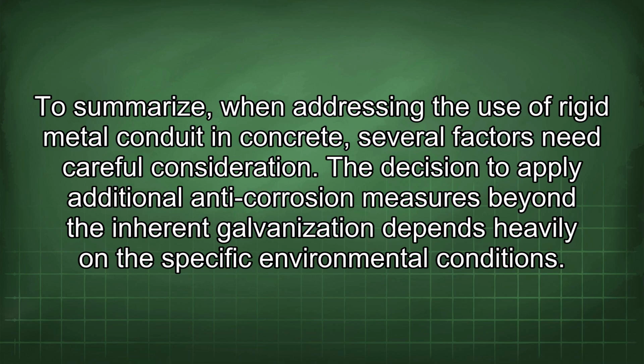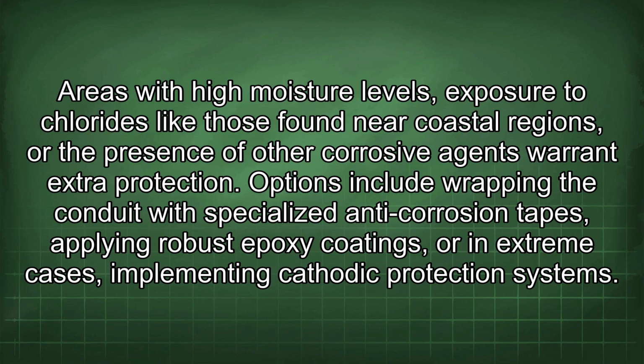To summarize, when addressing the use of rigid metal conduit in concrete, several factors need careful consideration. The decision to apply additional anti-corrosion measures beyond the inherent galvanization depends heavily on the specific environmental conditions. Areas with high moisture levels, exposure to chlorides like those found near coastal regions, or the presence of other corrosive agents warrant extra protection. Options include wrapping the conduit with specialized anti-corrosion tapes, applying robust epoxy coatings, or, in extreme cases, implementing cathodic protection systems.